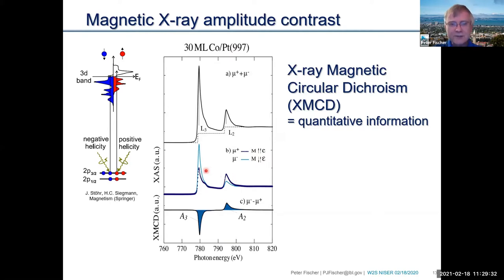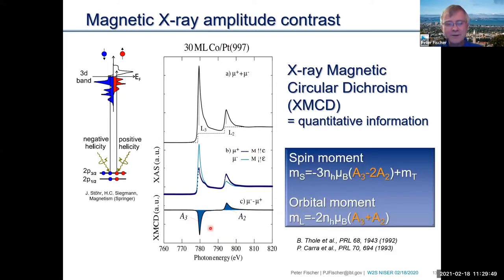And interestingly, if you just compare the spin-orbit partners, the L3 and L2, which is just the difference between 2p3/2 and 2p1/2, it flips the sign. So you go from a negative excess at the L3 to a positive excess at the L2. Now, what that means is that by analyzing those two areas, the A3 and the A2, you can derive quantitatively, by just looking at absorption spectroscopy, spin moments and orbital moments in an element-specific way, because that happens only at a very element-specific photon energy. This was a big breakthrough in the 1990s when this was discovered, and people were able, by doing this relatively simple experiment of X-ray spectroscopy, turning on the polarization and measuring magnetic materials, to arrive at spin and orbital magnetic moments, fundamental quantities of magnetism.